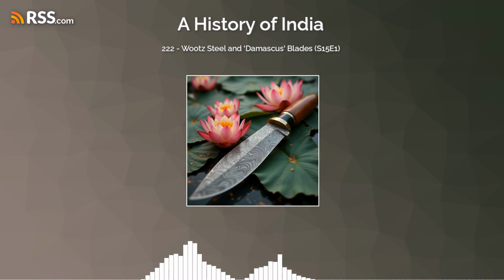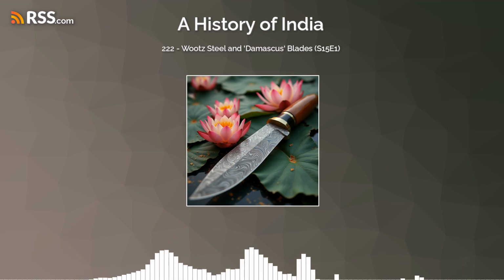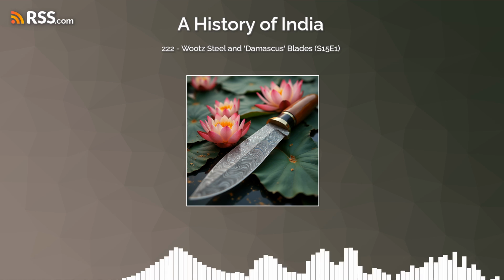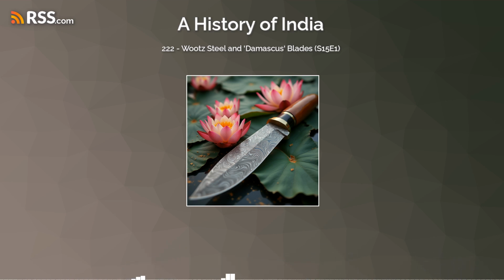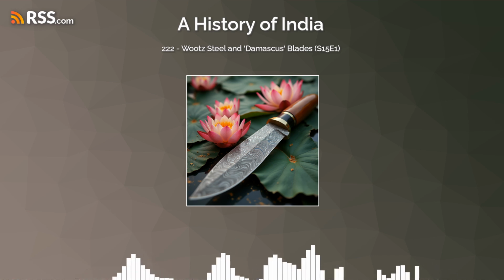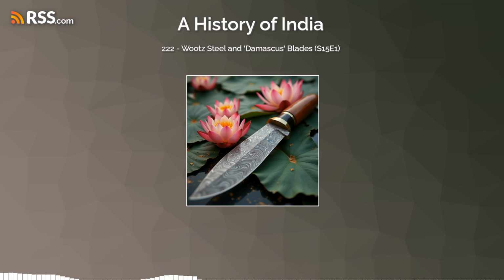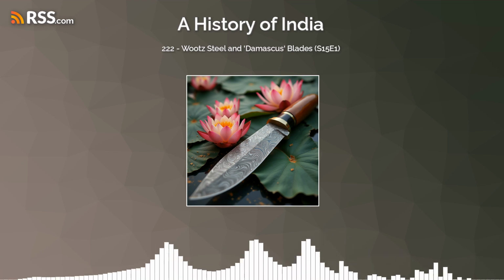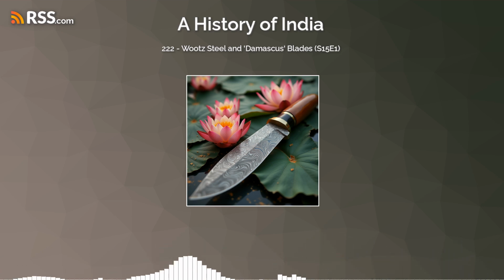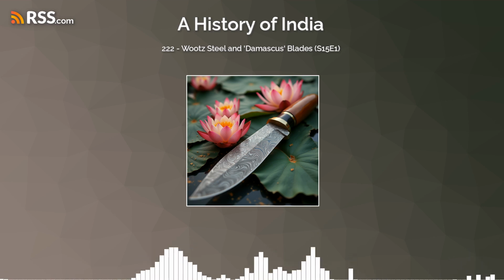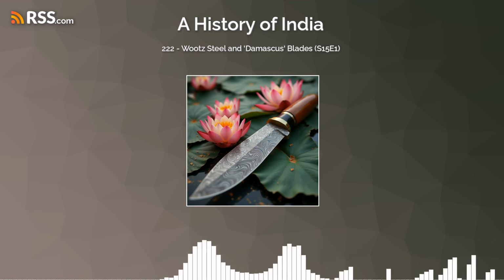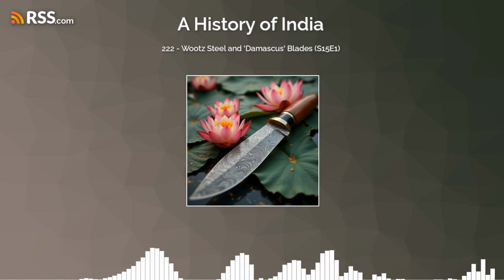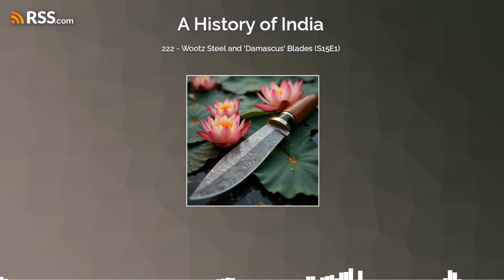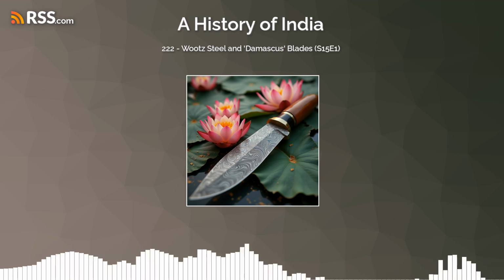They knew they had to forge the steel within a very specific, relatively narrow temperature range. Modern science suggests somewhere around 850 degrees Celsius down to maybe 650 degrees Celsius, a sort of dull red heat, not the bright yellow or white heat you'd use for a lower carbon steel. Why was overheating so bad? If you heated Wootz too high, you'd dissolve all those carefully formed cementite structures back into the high-temperature austenite phase. Then, if it cooled too quickly from that point, it could form extremely brittle structures, and yeah, it would just crumble under the hammer. They knew, somehow, not to do that. So forging wasn't just shaping, it was a critical heat treatment too.